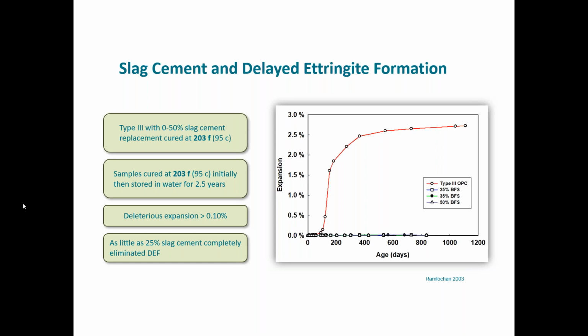It's very obvious to me that if you need to cure concrete at high temperatures to solicit early strength gain, even a small amount of slag cement can act as an insurance policy against this rare but detrimental form of sulfate attack in DEF. So I think this is a wonderful illustration that shows how beneficial something like slag cement can be, even at fairly reasonably low replacement levels. So next slide.